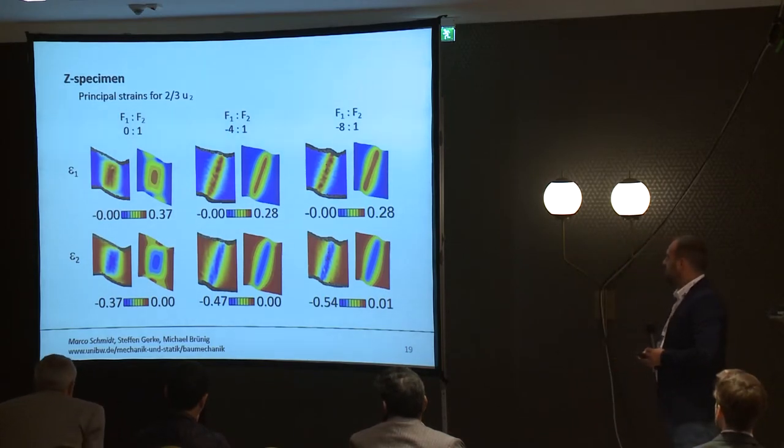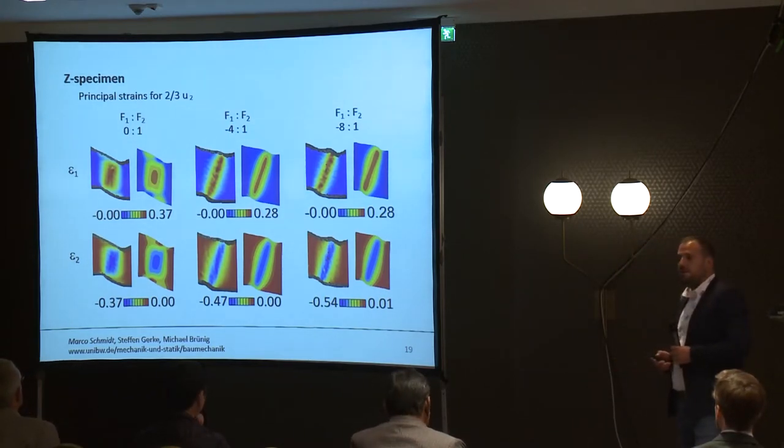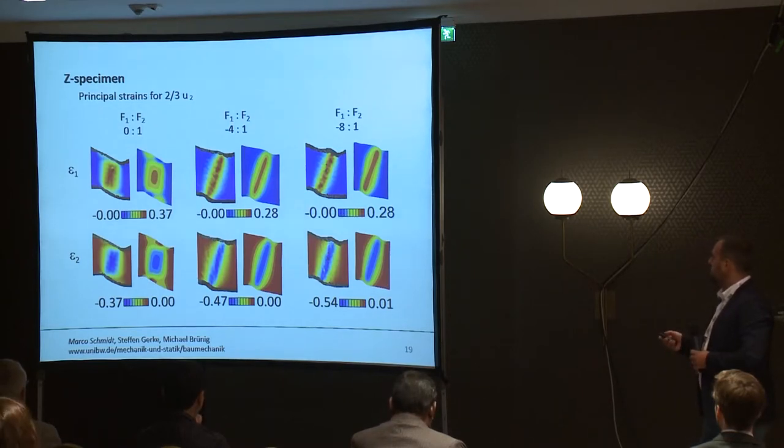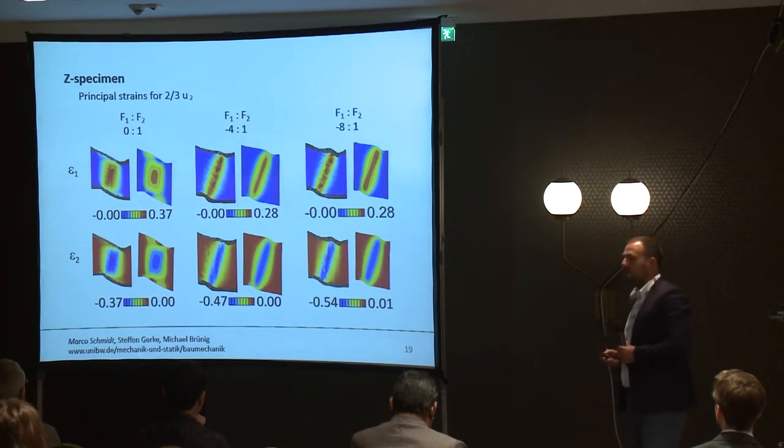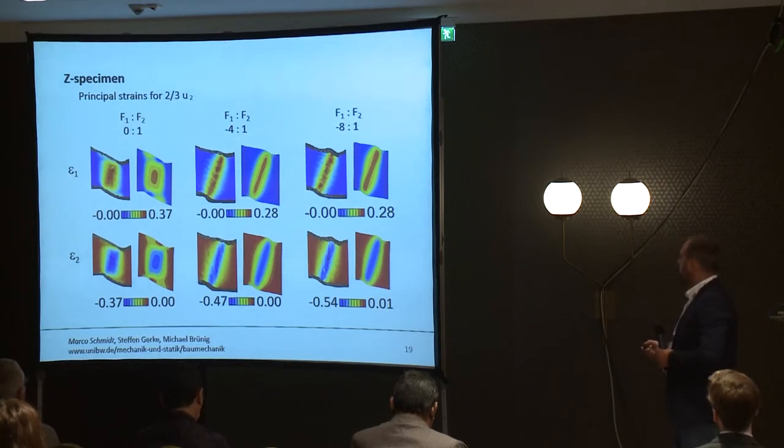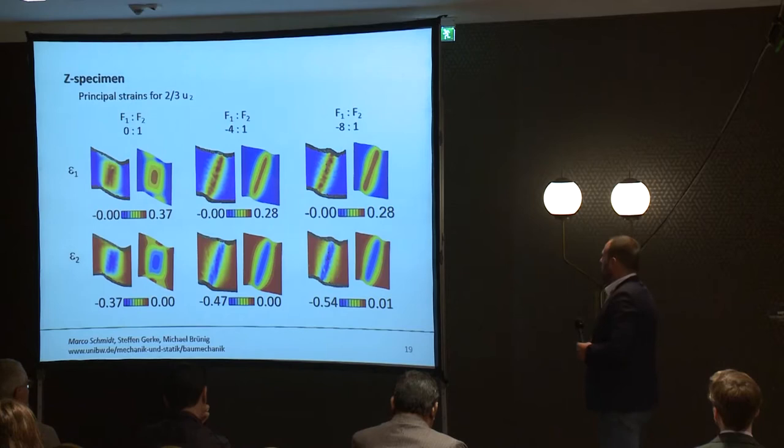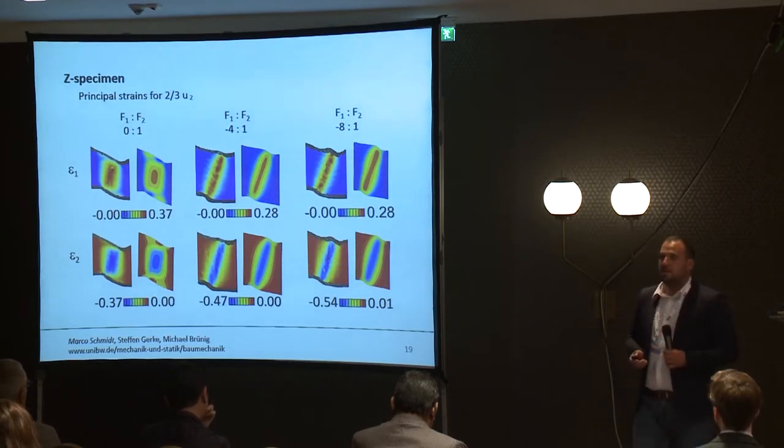For a more detailed evaluation, I will confine myself to three load cases below: the pure shear test and two shear compression combinations with the load factors minus four and minus eight. You can see there is again a very good agreement between experiments left and numerical simulations right for all three load cases. You can also see that with increasing compression, the strains are more localized and a strain band is developed.